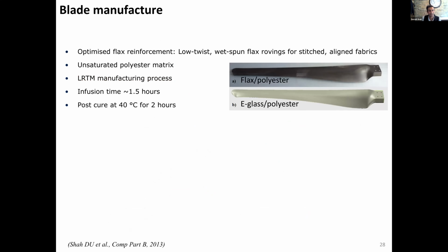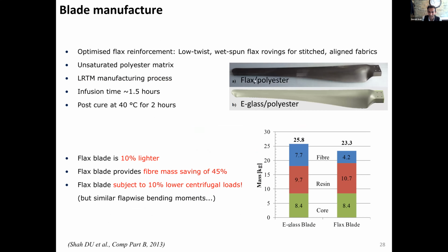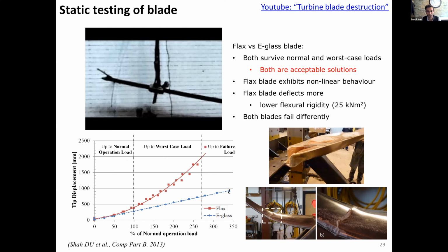I'll quickly rush through some of the testing that we did. So we made a full-scale blade, which was about 10% lighter. We couldn't get more fiber in it because it was lofty, and as I mentioned, getting lots of fiber in there is a challenge. The other aspect was during the testing, we quite clearly realized that although the flax blade could surpass the necessary worst case and normal survival loads based on the IEC 61400 standard, we noticed a nonlinear stress-strain tip displacement behavior. And this would in theory be a failure because of a stiffness drop, or actually it would hit the tower because of the tip displacement. So those are things that we still need to design and develop further.